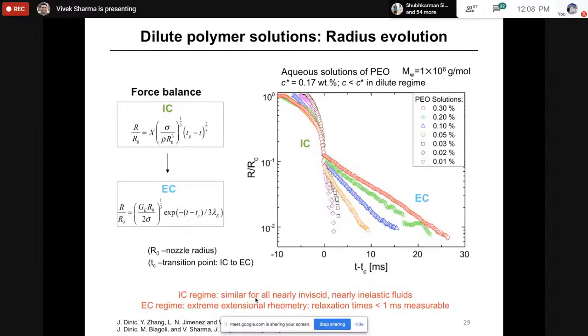Here, what we see very nicely is if we plot radius evolution in a shifted time scale such that TC represents a time scale at which there's a transition from inertia capillary to elastic capillary, what you see is all these solutions, in spite of slight difference in their viscosity, because inertia capillary response only depends on surface tension and density, they approach asymptotically the same behavior. That's fantastic. And then in the elastic capillary regime, there's a concentration dependent increase in breakup time or filament lifespan, and the slope changes, meaning relaxation time changes.